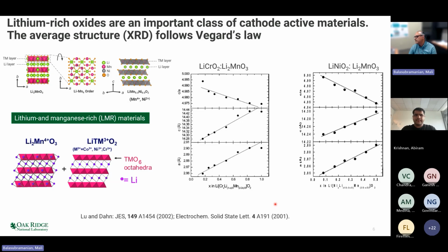It has been used, for example, in semiconductors to understand band gaps and how band gaps will change with doping. Now, while Vegard's law is valid on the average scale, as has been shown by Professor Dahn's work, it is not clear that mixing these things on an atomic level will actually create a fully disordered solid solution, which will follow Vegard's law. Additionally, when you have ions or atoms of different ionic sizes, you expect that these atoms will induce local disorder or local distortions around their sites. In order to study that, one needs a local probe to follow it.